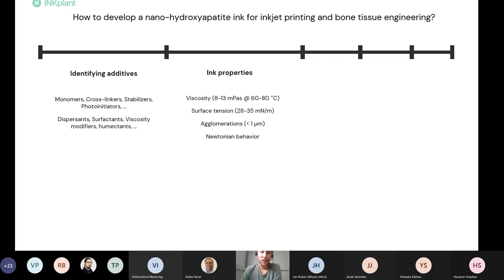Surface tension should be about 28 to 35 millinewton per meter in order for the ink to wet the nozzle plate of the printhead and also to wet on the substrate. When we're talking about an ink that contains nanoparticles, one should be able to hold agglomerations below one micrometer. And as very high shear stresses act on the nozzle plate, usually Newtonian fluids are used.